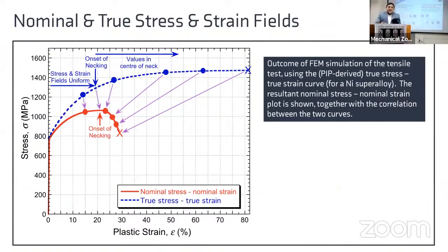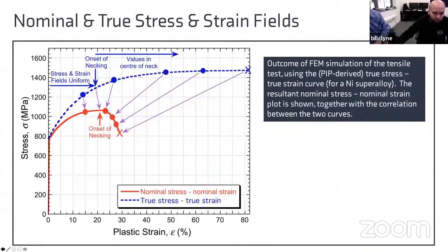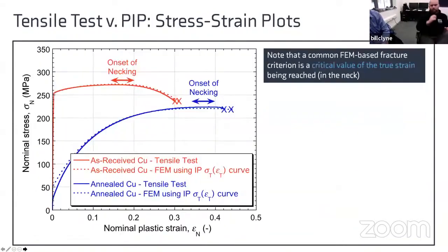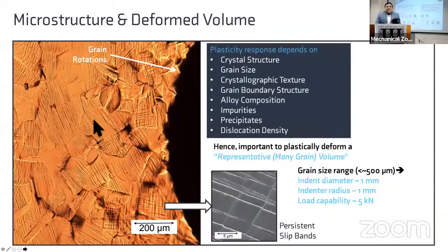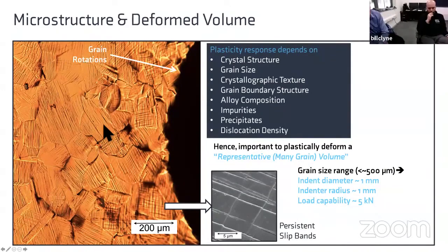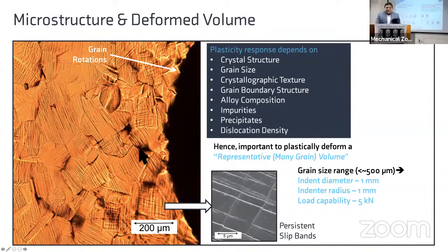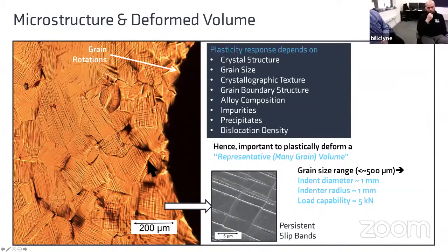There is one point you might like to note there, which is that if you do get a reasonable finish, you might see some interesting things. Like here, for example. That's just the free surface around the indent, and it was well polished beforehand. You start to see what look like persistent slip bands, where lots of dislocations have followed each other and reached the free surface. If you look carefully, you can see deformation twins or prior annealing twins, and you also see grain rotations. This kind of thing becomes clearer if you have created a polished surface to start with. But in terms of actually doing the test, you don't need a polished surface.